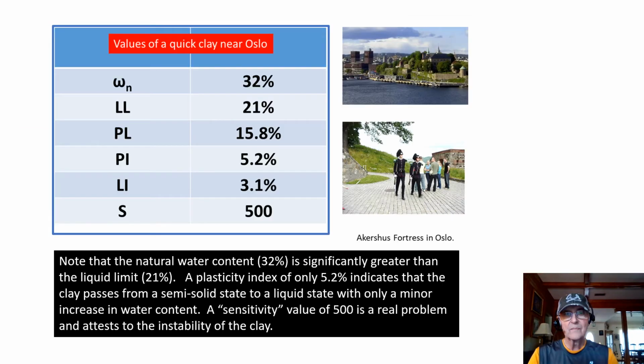Landsliding can occur. Here you can see some of the typical values of a quick clay near Oslo. Please note that the natural water content, 32%, is much greater than the liquid limit, which is 21%. The plasticity index is only around 5%, and that indicates that the clay passes from a semi-solid to a liquid state with only a minor increase in the water content. And the sensitivity value of 500 is a real problem and attests to the instability of this clay.